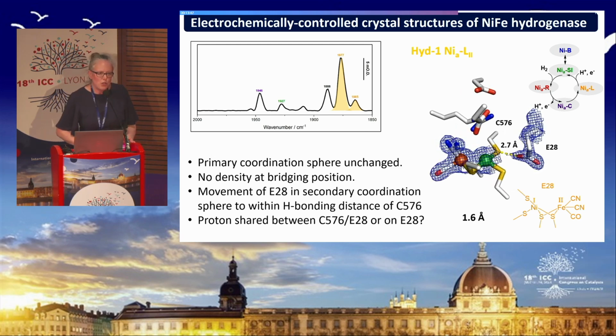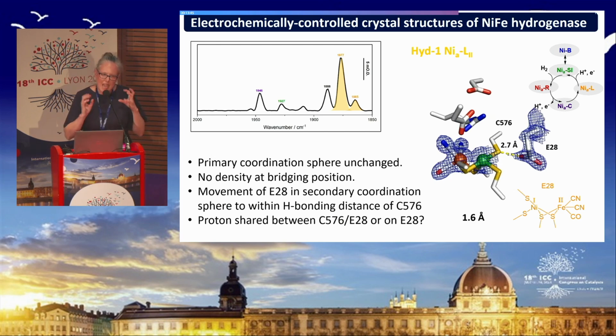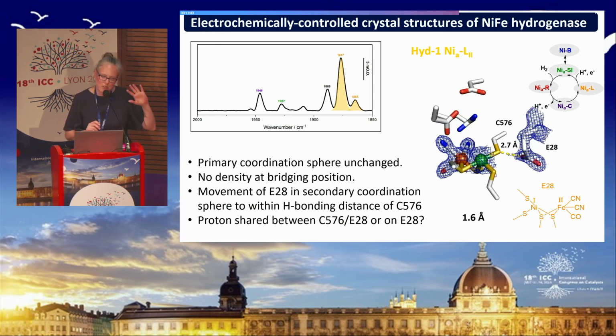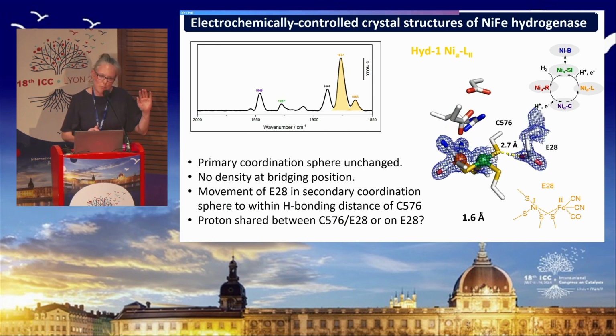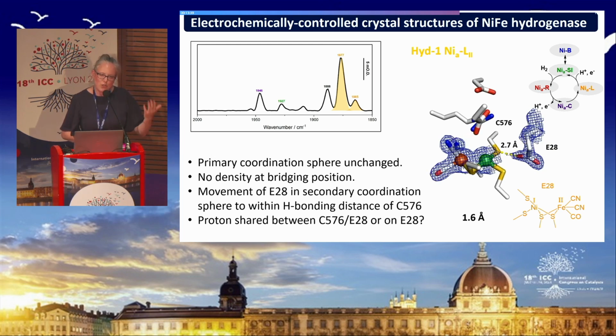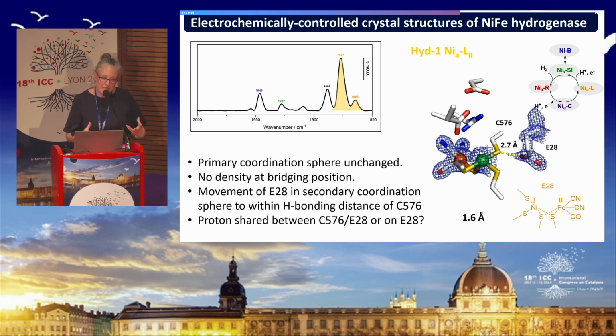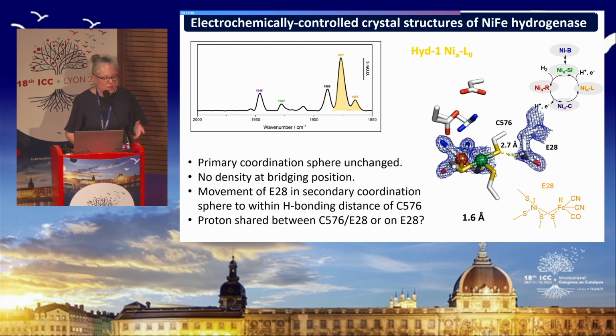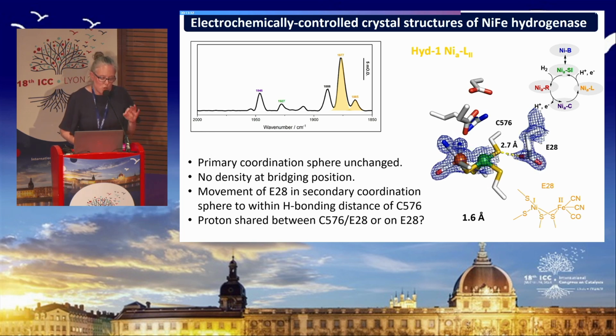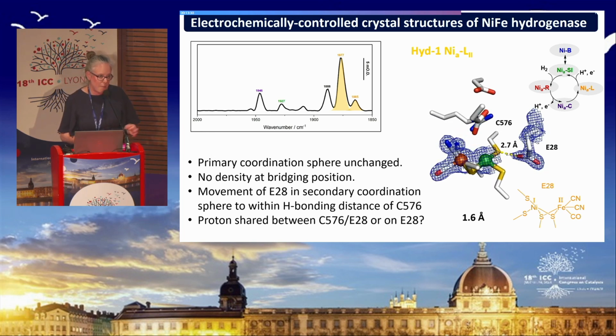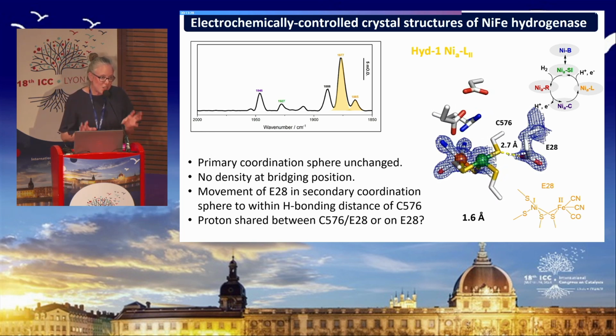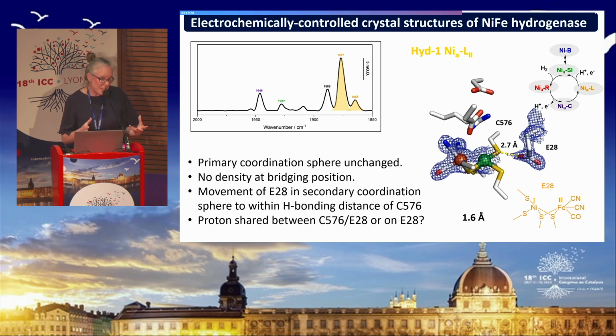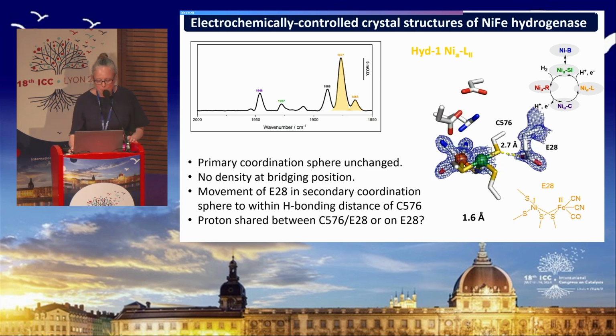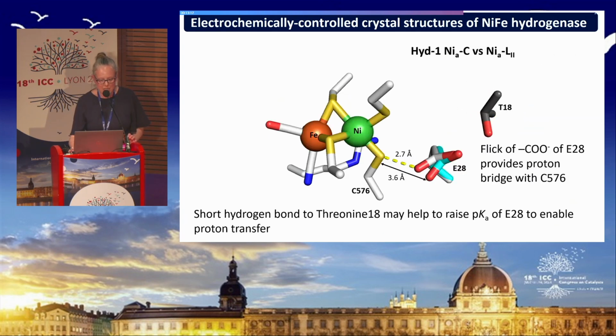So I think this gives us really direct evidence that that glutamate residue can be involved in proton transfer in hydrogenase. And it shows us that we've got this active site that is absolutely rigid, and what nature has done is found the most subtle movement possible in order to allow proton transfer, which does need a little bit of mobility within a protein. So I think this is an enzyme that's tuned for very fast, low reorganization barrier, according to Marcus theory, electron transfer, but very subtle movement to allow proton transfer. So that was quite an exciting finding there.